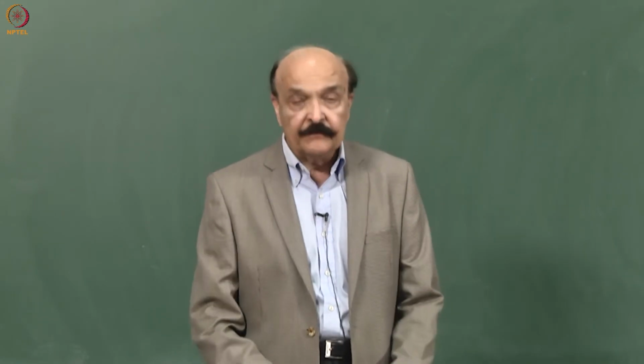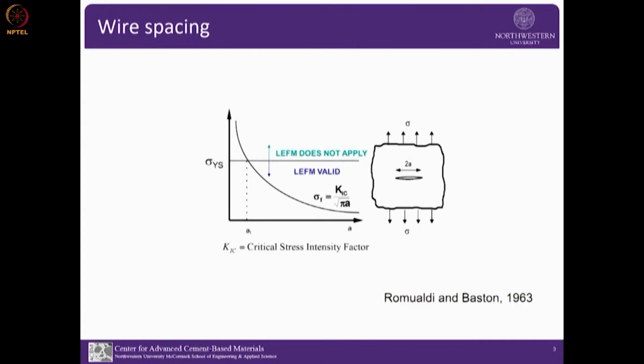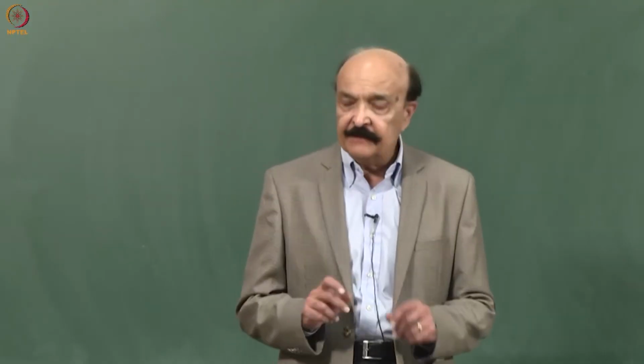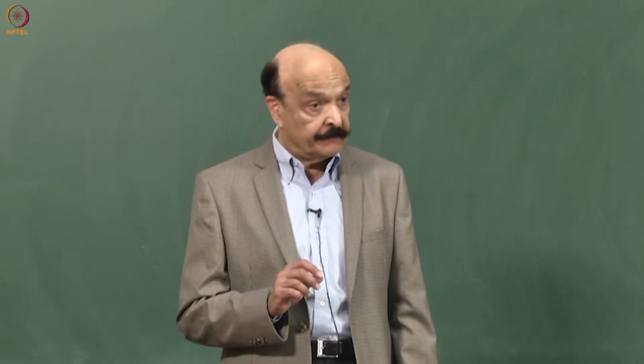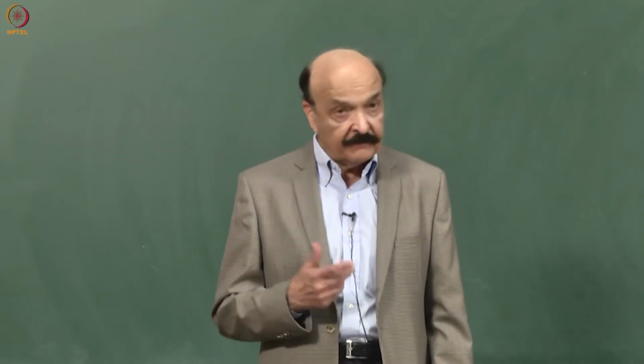So let me first start with the development of steel fibers in the US. The concept behind the development, according to Romualdi and Batson, who were at Carnegie Mellon, is that concrete is a brittle material, and a brittle material obeys the Griffith fracture criteria, that is, fracture strength is inversely proportional to flaw size. Smaller the flaw size, considerably higher fracture strength. So they said that if you use randomly distributed fibers, they can be closely spaced, so you can increase the tensile strength. So a very intriguing idea.